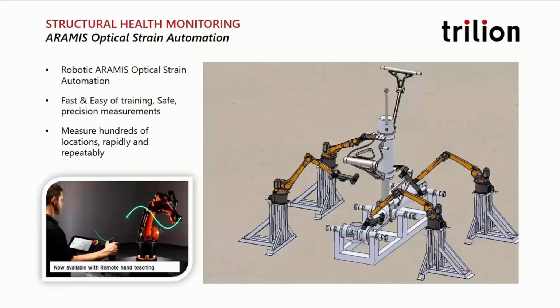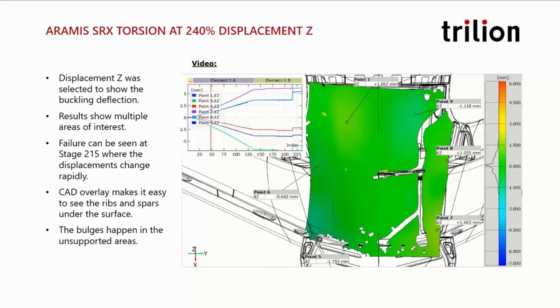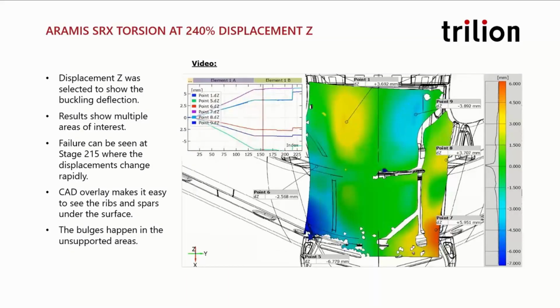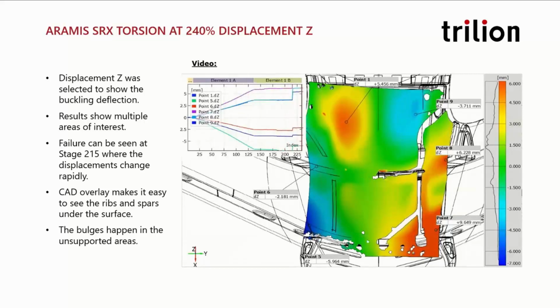For complex structures like landing gear, we do ARAMIS robotics. And so here we're doing the automation of the measurements during the testing. And you can be looking at hundreds of measurement areas with thousands of measurement points to really understand complex structural response. In this case, this is a large wing structure, a body structure actually between 2 wings of a vehicle. And we can see the CAD overlay and the true displacements that are happening across the field of view. This is about a 6-foot field of view during this loading of the component.